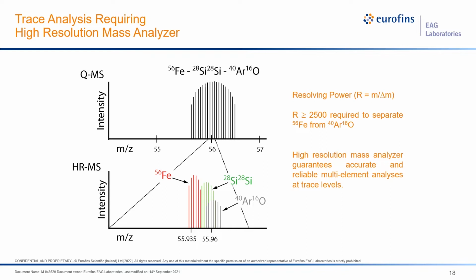So you will be forced to have elevated detection limits. Now, if we have mass resolution over 2500, we can separate those mass species, iron 56 from the 28 silicon dimer as well as from argon. With that, it enables us to do accurate, reliable multi-element analysis at the trace levels.